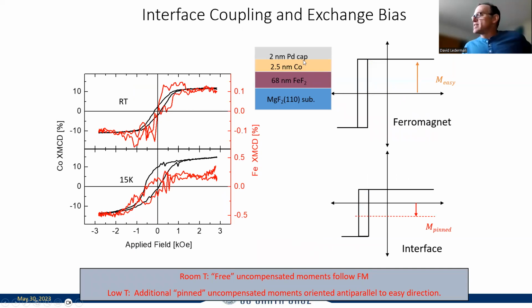So what we did is we made a sample that looked like this. We had iron fluoride grown epitaxially on magnesium fluoride. Magnesium fluoride has the same rutile crystal structure as iron fluoride, so we were able to grow this epitaxially. Then we put cobalt on top. This is the ferromagnet, this is the antiferromagnet. We capped it with palladium because we didn't want to oxidize the cobalt and create another antiferromagnet, which would complicate things. This was all done in situ so that we didn't have to oxidize anything. The palladium just keeps this from oxidizing. And so this is the signal.